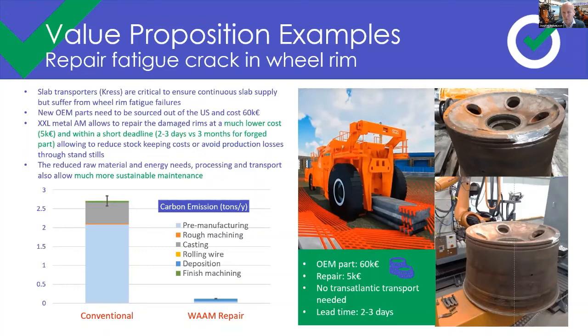This resulted in a huge saving for the customer, as you can see on the slide. The new part would have cost around 60,000 euros, while the repair was only 5,000 euros. So there's a massive saving. But even more important, these wheel rims are used in Europe, but they actually are produced in the US. So they needed to be transported from the US to Europe, which has, of course, an ecological aspect, but also a lead time aspect, while the repair only took 2 to 3 days to be completely completed.